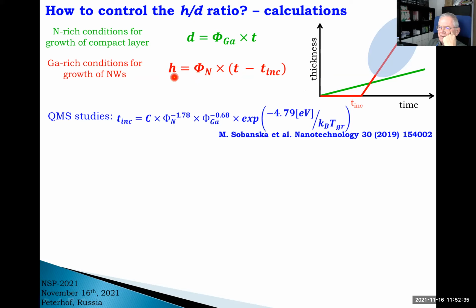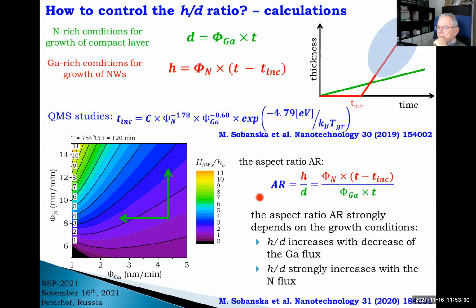gallium-rich conditions, so the length is proportional to nitrogen flux and time, from which we need to subtract the time needed, the delay of nucleation onset, the incubation time. So we have this line, and we are looking for this range of parameters. We know how incubation time depends on growth parameters, so we can put this right here. And we calculate the aspect ratio, which is the ratio of the length of wires to the thickness of the compact layer. And having this, we create a map.